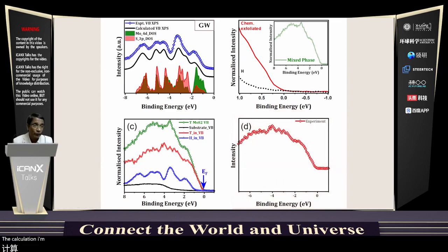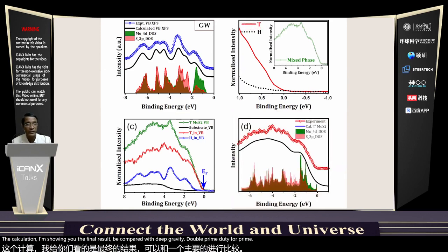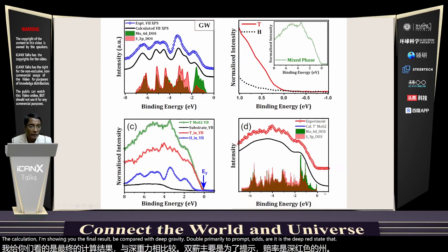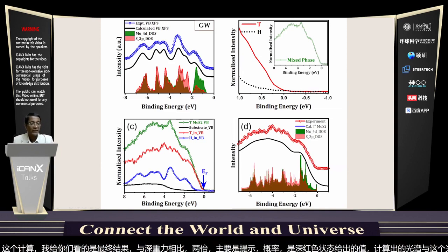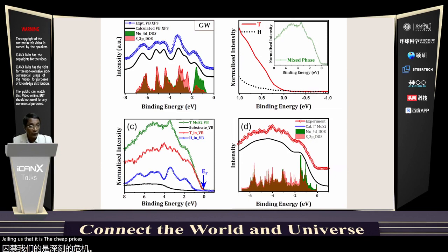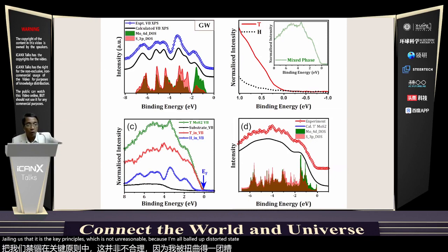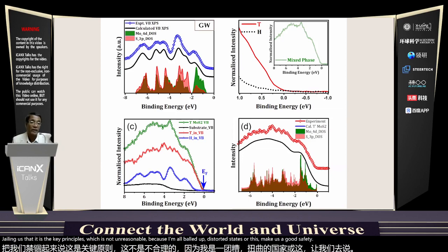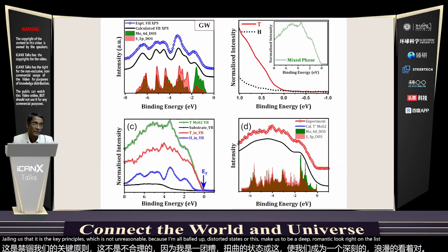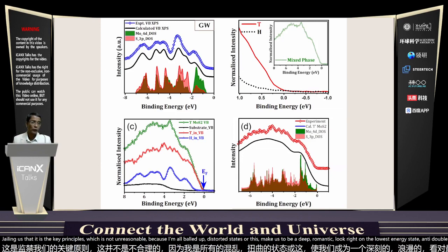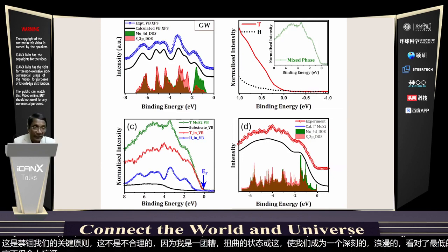I'm showing you the final result. We compared with T prime, T double prime, T triple prime. It turns out it is the T prime state that gives the calculated spectrum that matches very well with this experimentally obtained valence band spectrum, telling us that it is the T prime phase, which is not unreasonable because among all the distorted, metastable states, T prime and T triple prime are the lowest energy states and T double prime is not. So it's not totally surprising that we are getting to the T prime state.